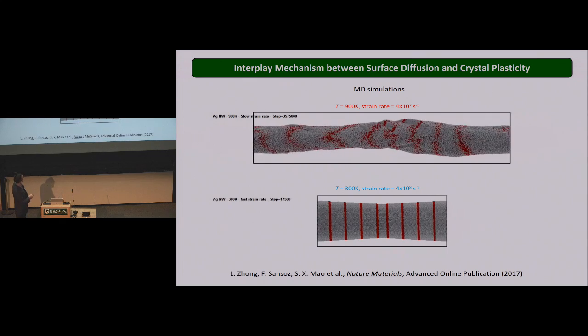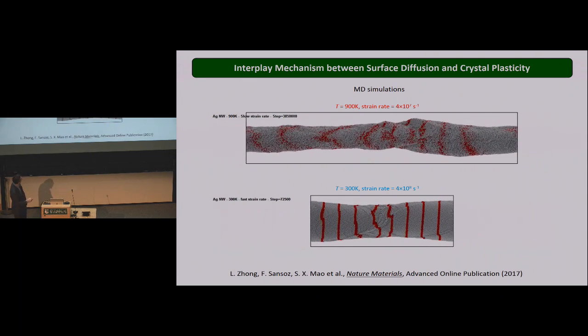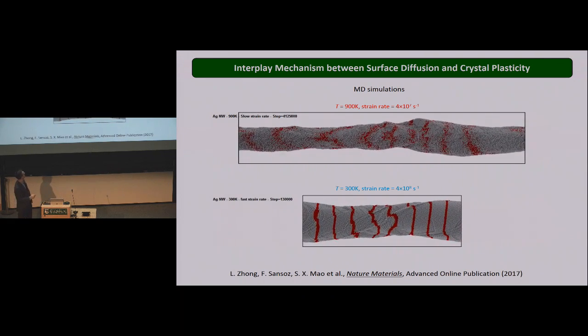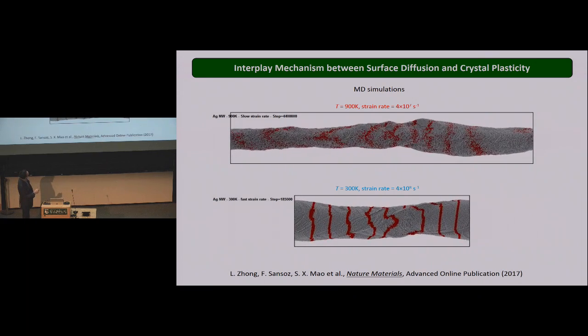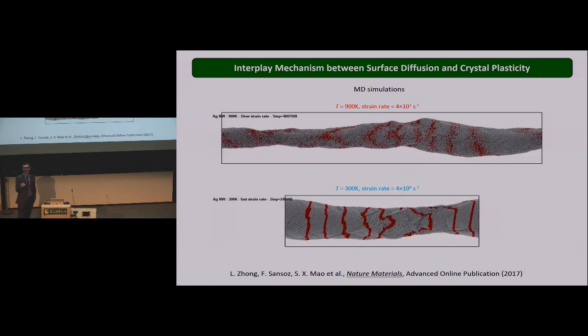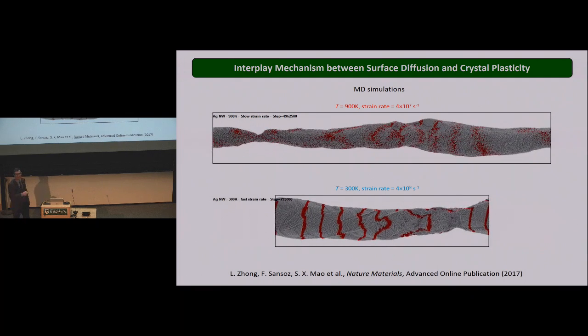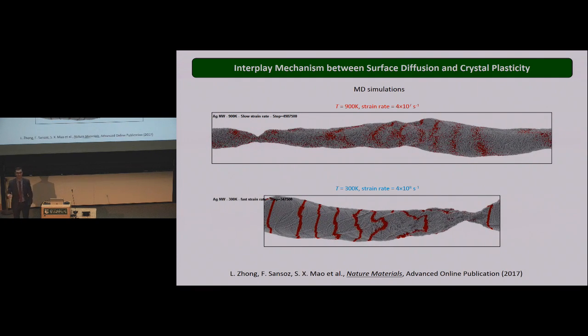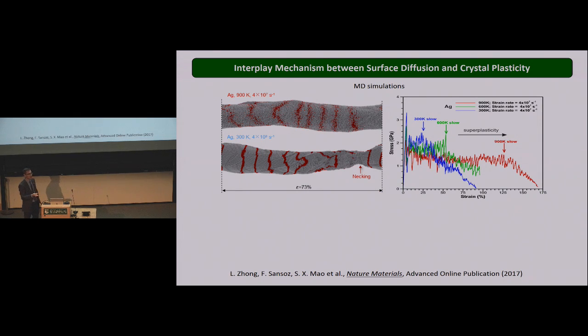And now the case at the bottom here is the same material, same model, but now I reduce the temperature and I increase the strain rate by a factor of 10. And so here there's no time for atoms to diffuse on the surface. All right? And what we find here is this case has necking relatively early in the simulation, while when we allow for diffusion on the surface, this wire keeps elongating to 100% and more in simulation. And then again, the advantage of using atomistic simulation, we can look at the detail.